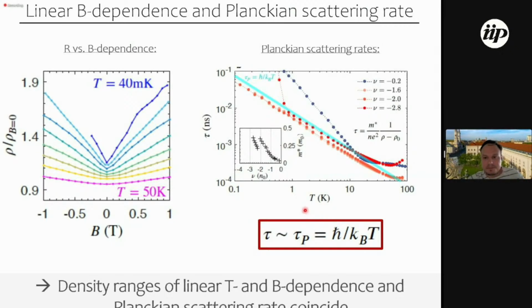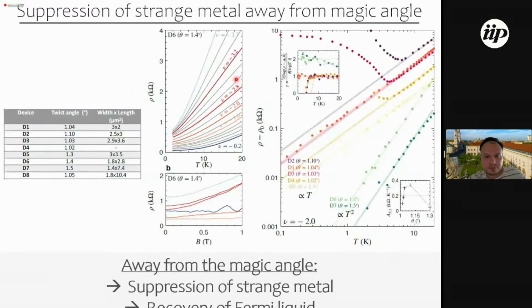And so basically, I think what's really striking is that even at 40 millikelvin, where in principle almost no phonons are populated anymore, where everything's supposed to be frozen out, where impurity levels we know are not sufficient for this type of scattering events, we end up having such an extremely fast scattering rate. And of course, the question is what can do the trick? And I will come back in a second to this.